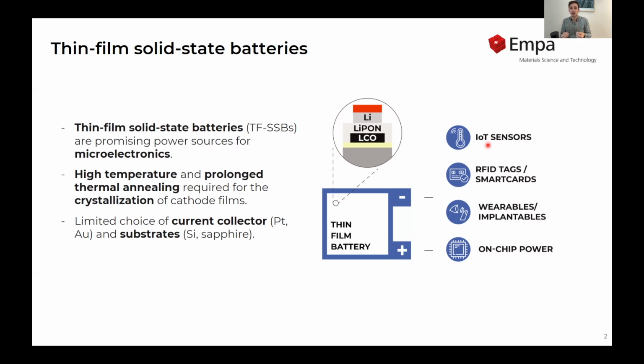In order to achieve good electrochemical performance, the cathode film needs to be crystallized at temperatures of about 700 degrees for prolonged times. However, this limits severely the choice of substrates and current collectors that can be used in these devices. Typical thin film batteries are fabricated on sapphire or silicon wafers with a platinum current collector, which of course has a big impact on the production cost.